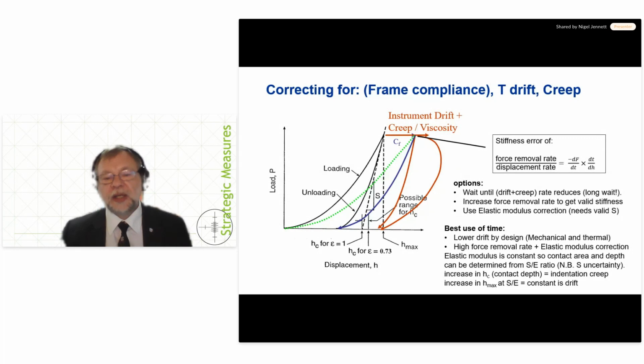You can do it. We did it at NPL. Over the first day or two we got down, and over the last day or two of the 5 days we ran, we got down to femtometers per second. It can be done in a temperature controlled laboratory, but nobody has that time to do a single indentation sensibly. So what do you do? The best use of time is to stop thermal drift happening in the first place. And that is a question for manufacturing, but it's also a question for your design of the experiment and how you set up the experiment so that you have the best thermal insulation and you don't cause drift in your own instrument. Then after that, it's using a high force removal rate, which is the obvious thing to do,